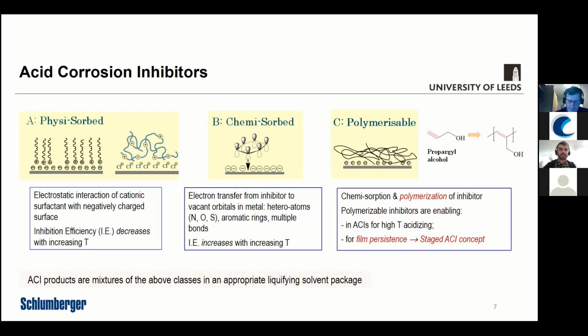So acid corrosion inhibitors, like I said, are essential. And corrosion inhibitors generally classify in a few different ways, depending on how they interact with the surface and the mechanism of inhibition they provide. So there's physisorbed inhibitors, which would be some sort of electrostatic interaction between the inhibitor molecule and the carbon steel surface. Chemisorbed inhibitors, with this electron transfer between the inhibitor and the metal.